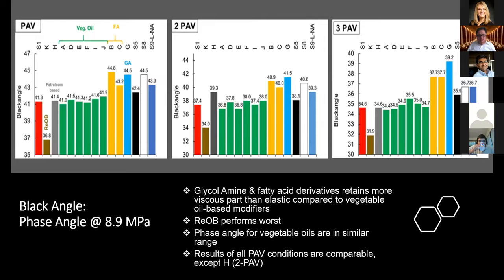Furthermore, the phase angle is a highly reliable measurement with a much lower variability than G* sin delta and can be determined easily from existing data. The phase angle also correlates well to delta Tc and confirms the relationship between phase angle and relaxation. The phase angle was also found to have a reasonable correlation to the viscosity ratio, indicating the applicability of phase angle to be used in the prediction of oxidative aging.